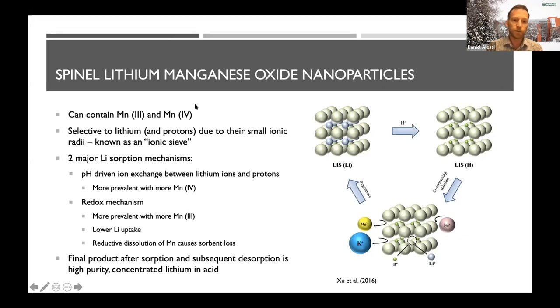And what you do is you precipitate this type of mineral, spinel lithium manganese oxide, in the presence of lithium. So this is the mineral here. And when you do that, lithium incorporates into the structure, and it makes this site where lithium exists in the structure of the mineral, and this site is very precisely the size of lithium. Now, lithium is relatively small, and there are many elements that are smaller than lithium, but in terms of ions in solution in a brine, there's really only two things that can fit into those sites. And that's lithium, of course, because you precipitated that.